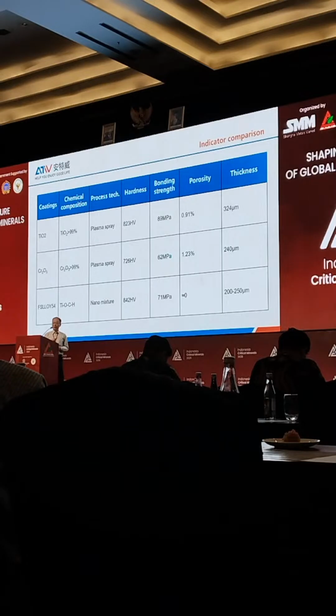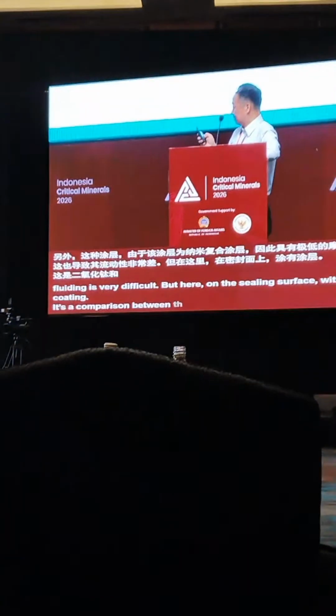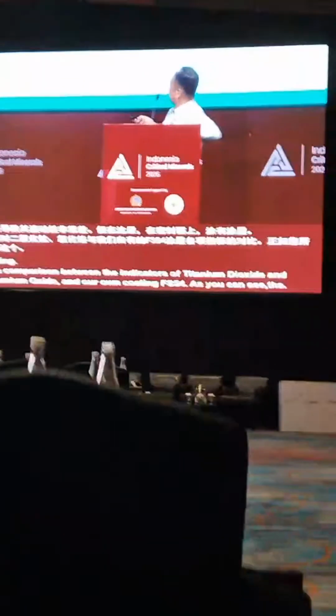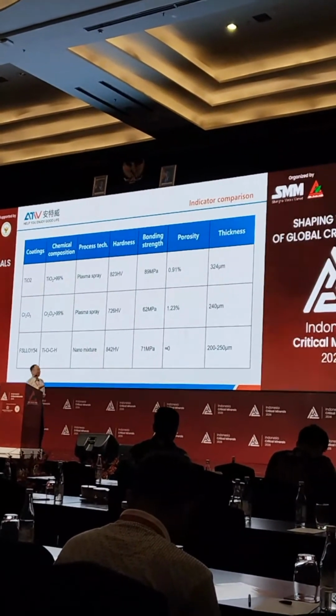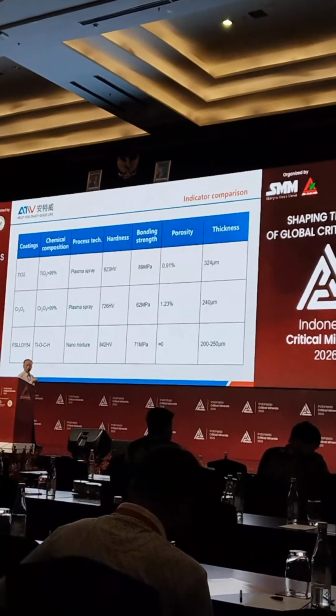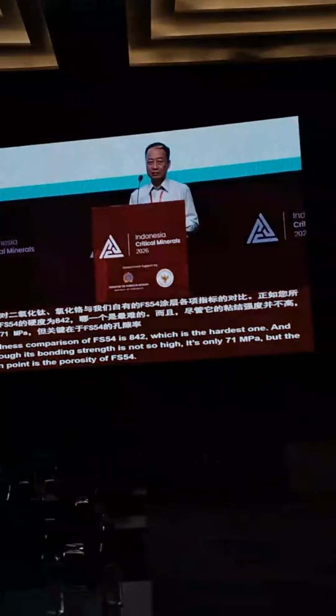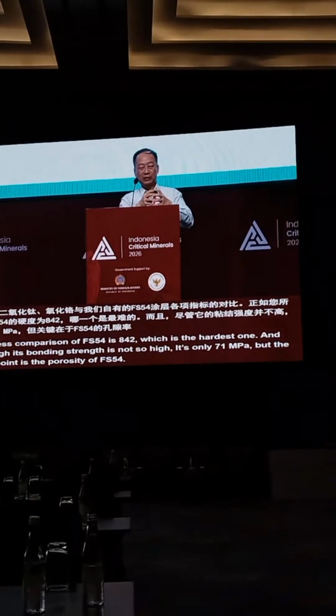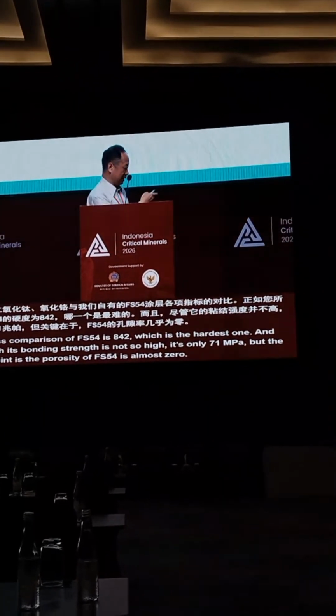This is a comparison between the indicators of titanium dioxide, chromium oxide, and our own coating FS54. As you can see, the hardness of FS54 is 842. This is the hardest one. Although its bonding strength is not so high, only 71 MPa, the main point is that the porosity of FS54 is almost 0. So that means the coating and the bonding material will be fully protected by this low porosity. So we organized our testing plan to